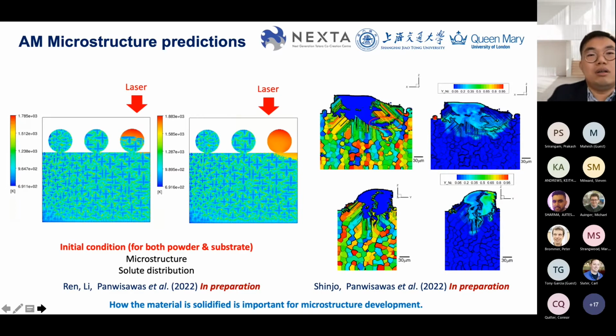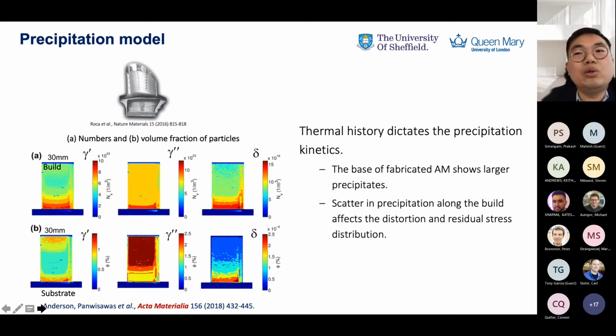Having said that, the thing we are going to do next is with regard to the precipitation model. As you know, there's some concern that the phase which is actually present in the printing is not as anticipated, because once you fabricate a nickel-based superalloy with high volume fraction gamma prime, you hardly see the gamma prime in the as-fabricated state. That is because of the non-equilibrium nature. And once you do some post-treatment, this will start coming up. And then how can we understand and maximize the use of the model in order to give some direction for the post-treatment? This work sheds some light on that.